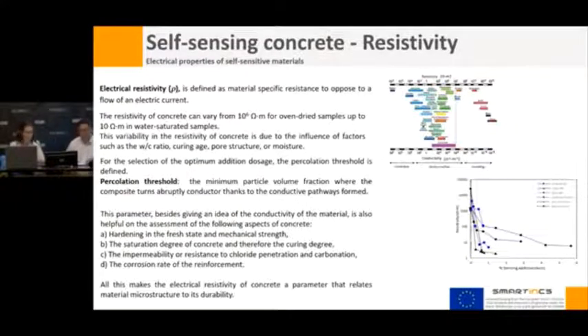We use the percolation threshold for that purpose. The percolation threshold is the minimum particle content which turns the material conductive because of the conductive pathway formed. As I told you, thanks to the advantages that this parameter presents, it is widely used in on-site works for durability assessment, like a quality control test.